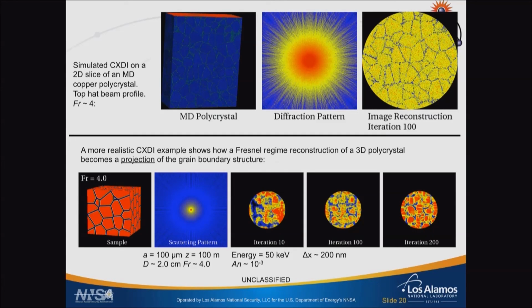So if you have a polycrystal, and unfortunately at this stage, most of my examples are theoretical examples in which we create an object, we scatter off of it, and we see what the diagnostic signals are. The theoretical models tend to be molecular dynamics models because that's what we're good at creating, these sorts of structures, and they're on arbitrarily wrong scales and so on. But again, you can take an MD polycrystal, you can create the diffraction pattern, and you end up getting an image reconstruction, which is essentially, in 2D, a projection of what the 3D object looked like.